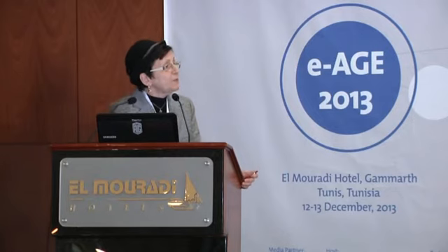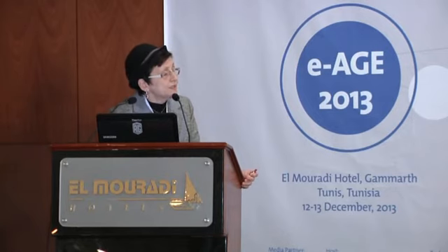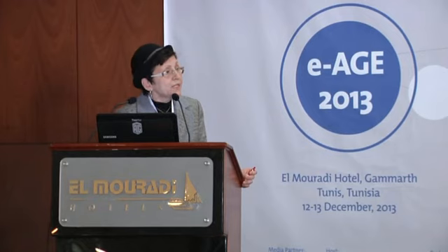For the buffer layer, we have used indium sulfide. Also, we can use zinc sulfide for the buffer layer. For absorber material, we have tin sulfide doped with copper and with indium. We have also doped it recently with silver. We have the ternary or quaternary materials. It is the ternary CIS material doped with gallium and the CZTS material.